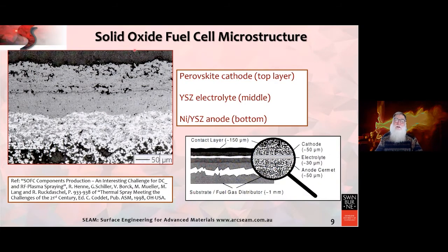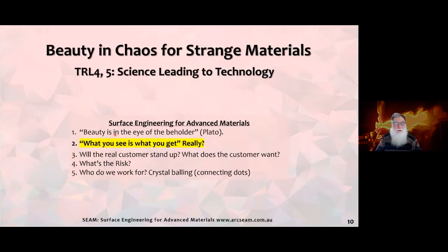So here's another example, a solid oxide fuel cell, all produced by thermal spray technology, where we have a perovskite cathode, an yttria stabilized zirconia electrolyte, a nickel yttria stabilized zirconia anode at the bottom. And what you can see is we have a material where we've got a composite structure, a dense structure, a porous structure with roughness. And this is just the epoxy embedded. But the point is that we are creating by thermal spray an absolutely wonderful composite on many levels within several layers, and all of these artifacts called porosity, cracks, or composite character, the cermet which is created here, for example, they all have specific functionalities which would be very difficult to impossible to form if thermal spray was not around. What you see is what you get. Now, really. So let's go back.